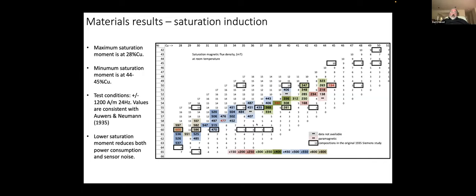One thing to point out, these black rectangles, which I've marked here, are the alloys that were made for the original Auwers and Neumann study. So if we're looking for things which ultimately are being resolved at the 1% level, their data are pretty coarse, and we really needed to fill it in order to find out what's really going on in this potentially interesting regime.